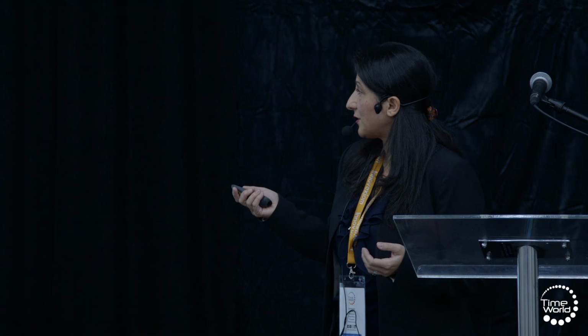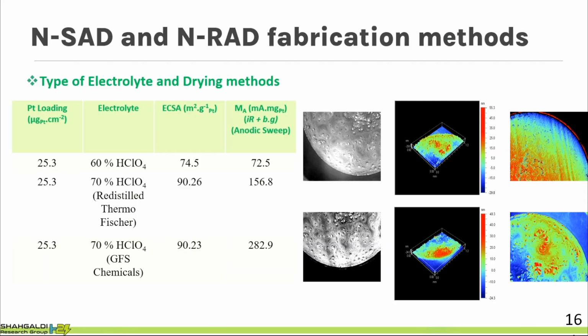I put this slide in because it's very interesting. We found that it's very important, when you're trying your catalyst, to use the same material from the same batch. We got two acids with the same purity from different companies, and we ended up with different results. So if you're working on catalysts and dealing with different screening, it's very important that you use the same batch of electrolyte to move forward and compare the results together.